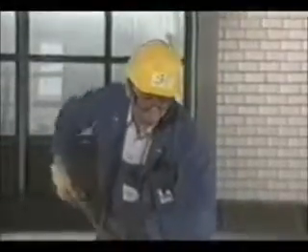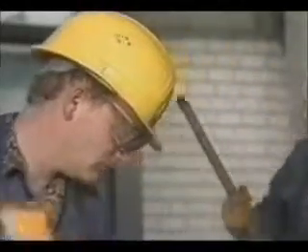In the next stage of the coating process, a laminate layer is laid. This is based on a polyurethane coating with outstanding chemical resistance, in which glass fiber matting is embedded. The combination of these materials is characterized by hardness and flexibility. It has good resistance to chemicals and gives the system a balanced load distribution capacity. The laminate layer is 2 millimeters thick.